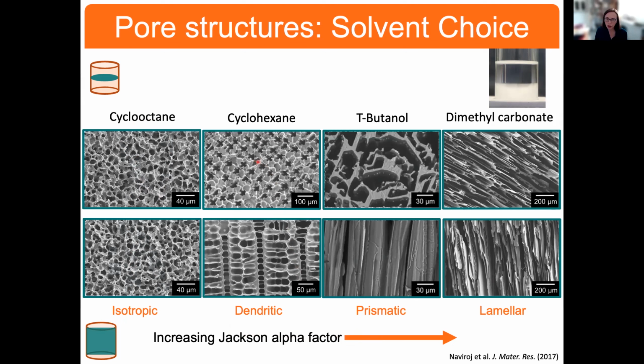But as we move now through this increasing Jackson alpha factor, we begin to see a great deal of difference in morphology. For example, with cyclohexane, looking down from the top, the dark areas are the pores, and they almost look like crosses. If we take the longitudinal view, we see that these dendritic pores have these long channels, but what you're seeing here are the negative of the side arms of the dendrite. So all of these pores here are outgrowths from the main channel of the dendrite, and they're negative. If we go further, we see prismatic pores that were produced using T-butanol as the solvent. And finally, with dimethyl carbonate, we see these lamellar pores looking down and then along the length. Highly anisotropic.